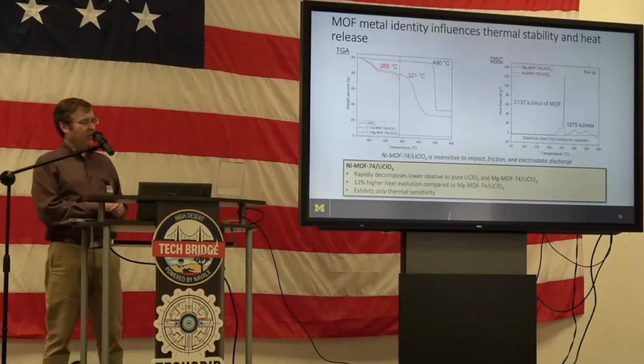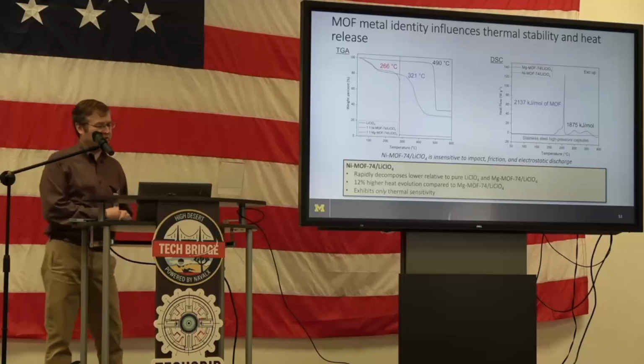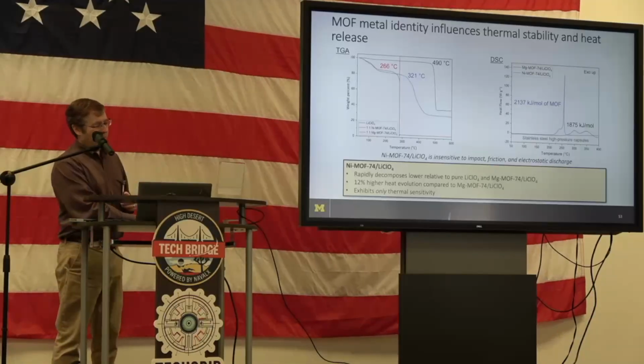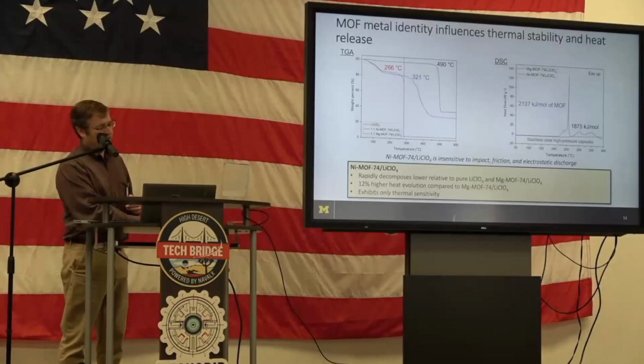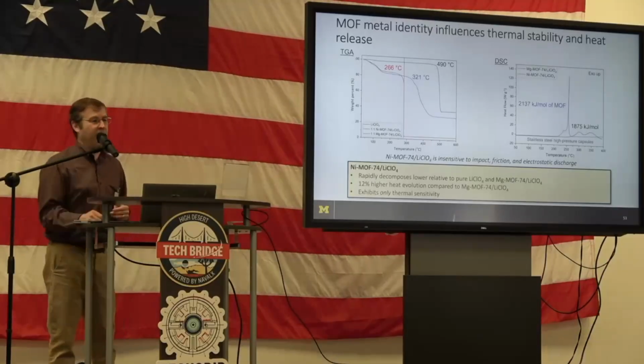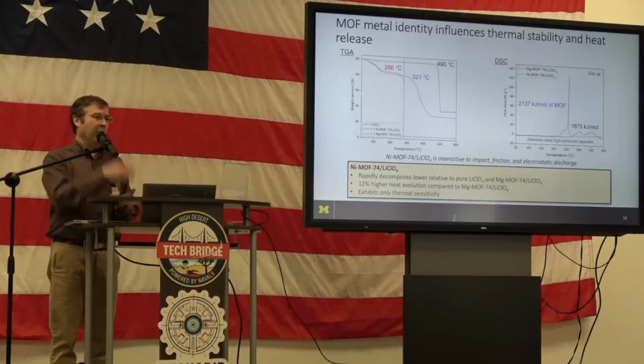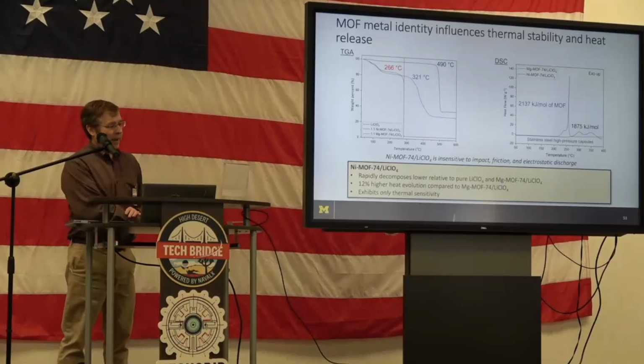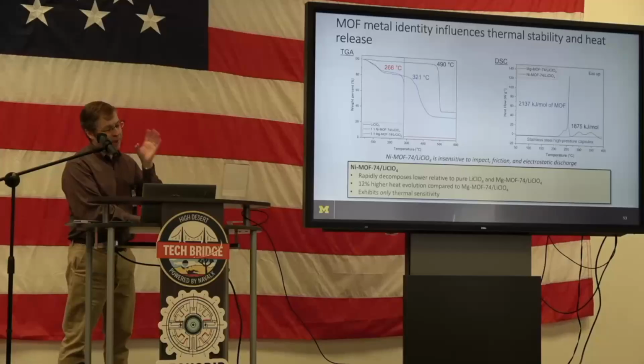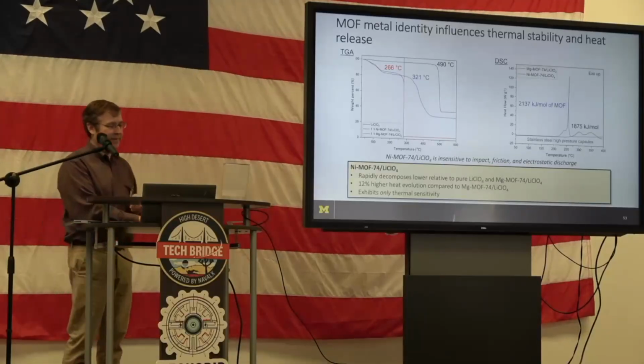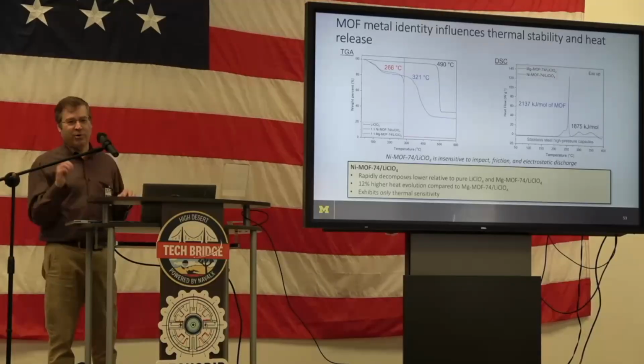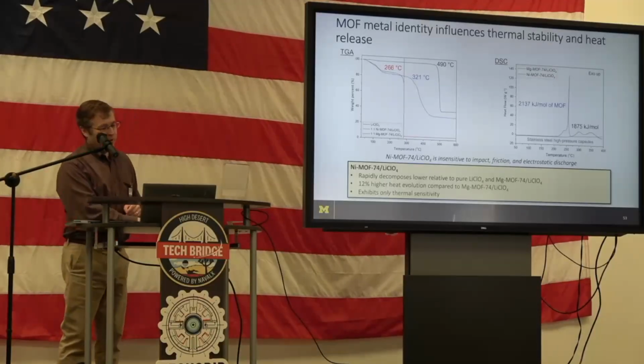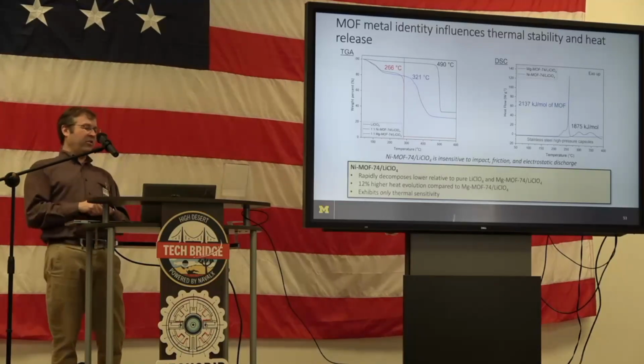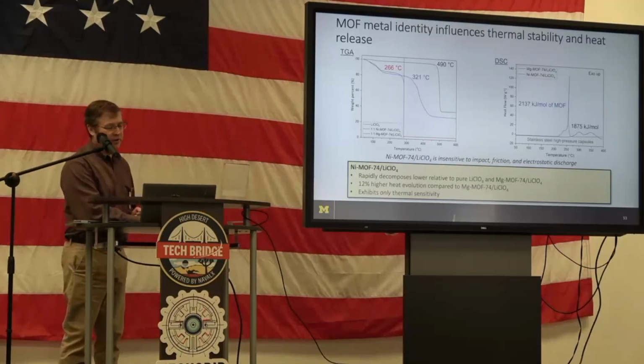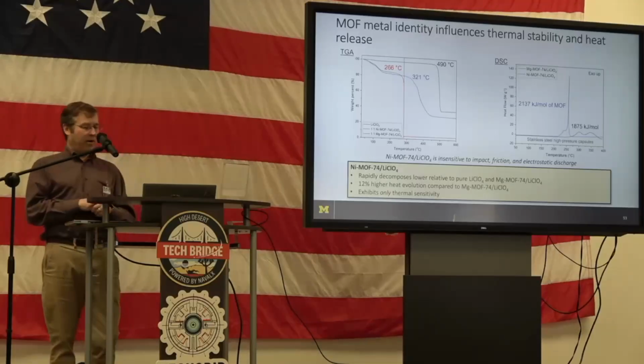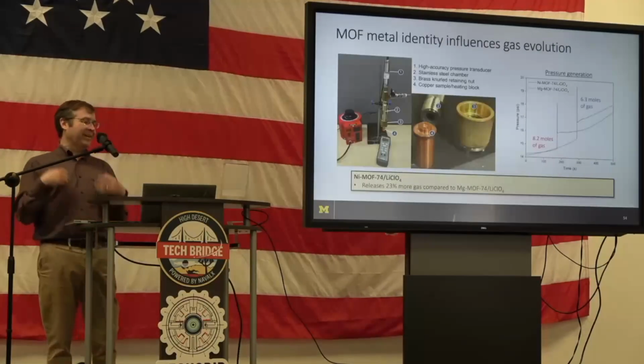So we can look at this by thermogravimetric analysis, and we can look at the heat evolution, and we find this signature that you need to go retrieve your TGA pan from the furnace because your stuff's blown up and came off the hook. And so that's what happens when we do it with nickel. With magnesium it's the loose powder, you're okay, and then lithium perchlorate, just straight oxygen. We do this in sealed pans, and we can see there's actually more heat evolution, and earlier, from the nickel MOF than the magnesium MOF. So that was interesting. We also looked at gas evolution.